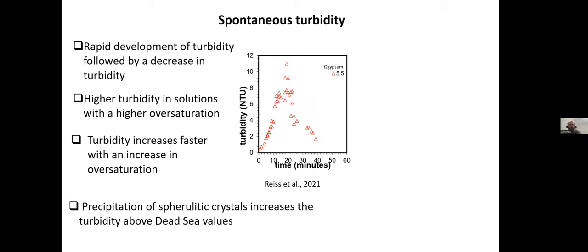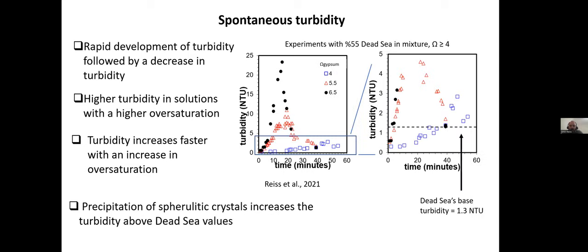So we could start by looking at the spontaneous turbidity. So we see here one experiment from the further from equilibrium conditions. We could add some more experiments with higher and lower oversaturation. And if we look at the graph at the right, there's a dashed line there with 1.3 NTU. This is the lowest value of turbidity measured in a monitoring station in the Engedi coast.